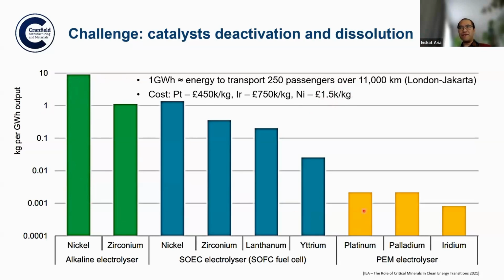In contrast, if we use platinum, the consumption of platinum is only in the order of gram or even milligram. Even though platinum is very expensive, this is 450,000 pound per kilogram, but because we only consume a milligram of that, for the same energy requirement, platinum is actually still cheaper than the use of nickel.